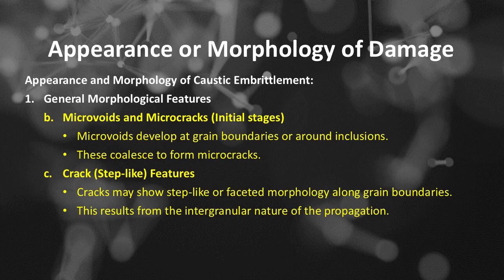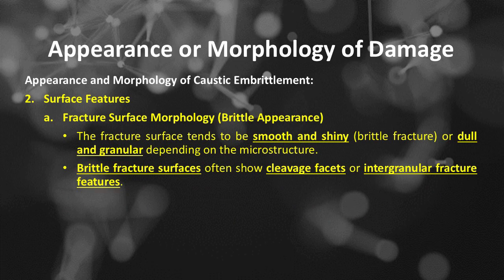Feature number C, crack features. Step-like features: cracks may show step-like or faceted morphology along grain boundaries. This results from the intergranular nature of the propagation. Appearance and morphology of caustic embrittlement. Number 2 is surface features, which includes, number A, fracture surface morphology or brittle appearance. The fracture surface tends to be smooth and shiny, brittle fracture, or dull and granular depending on the microstructure.